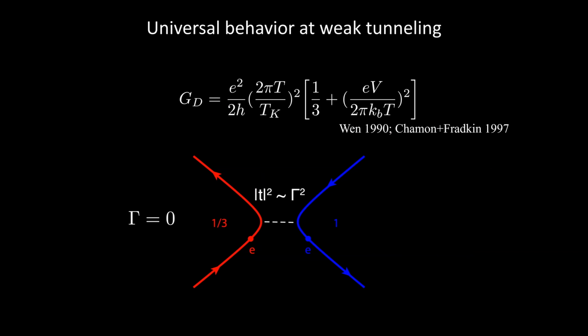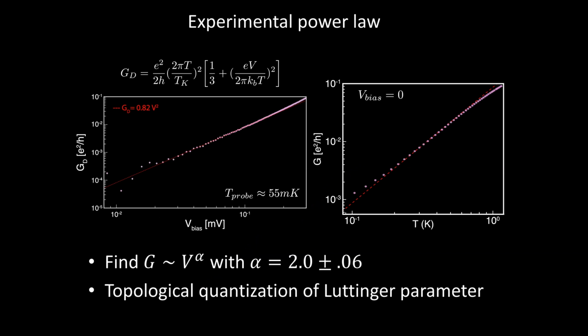Okay, but can it be quantitative? Right? There are very quantitative predictions in the universal low temperature, low voltage bias regime. You expect T squared and V squared power laws, and that's it. Right? Nothing else. If you go to low enough energies, that's what you're supposed to see. And if you just do the experiment, no tune-up, it just works perfectly, right? You just get T squared and V squared. It's what you're supposed to do.